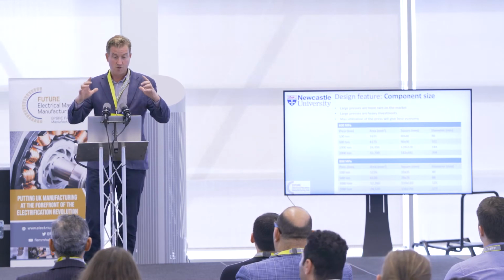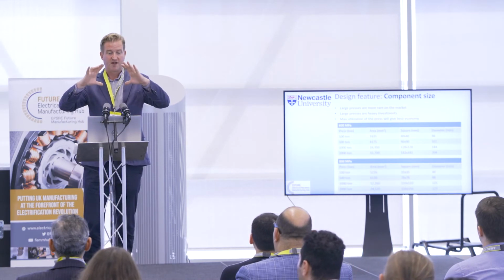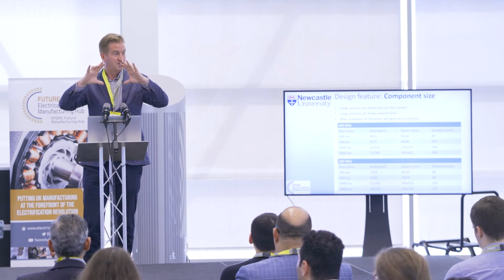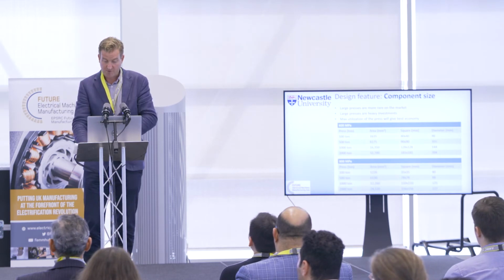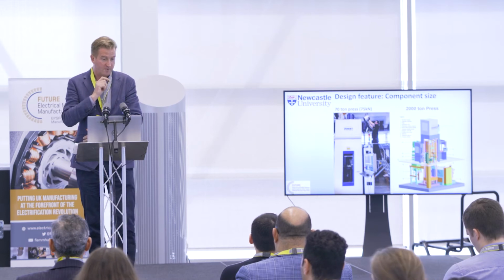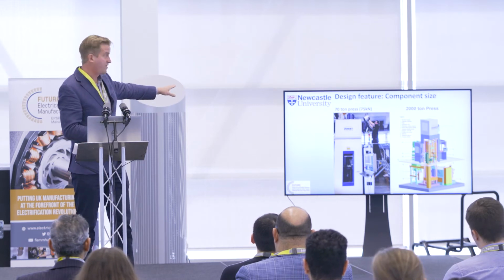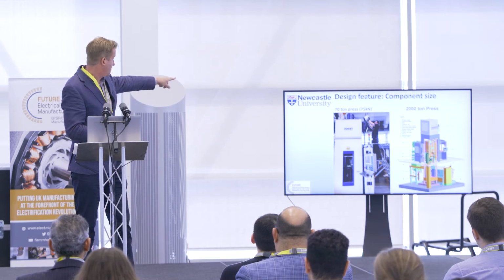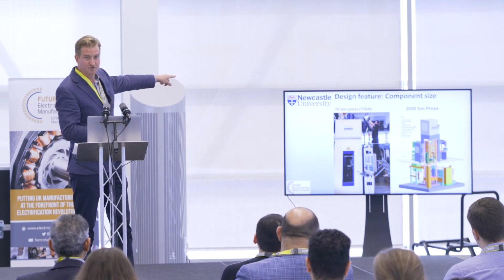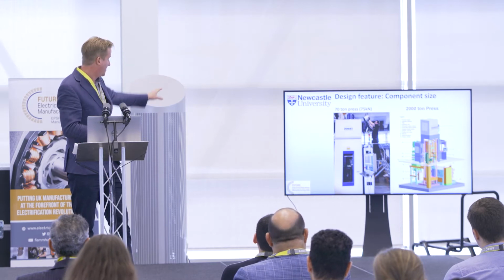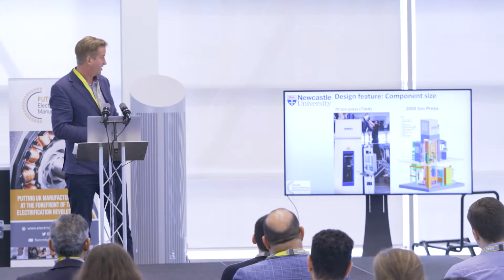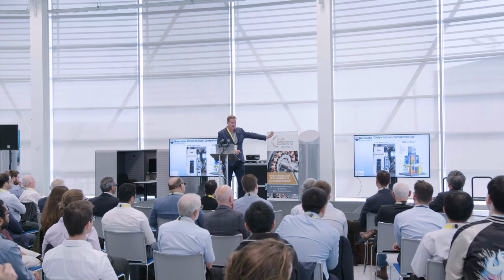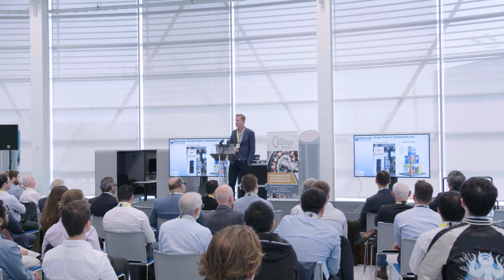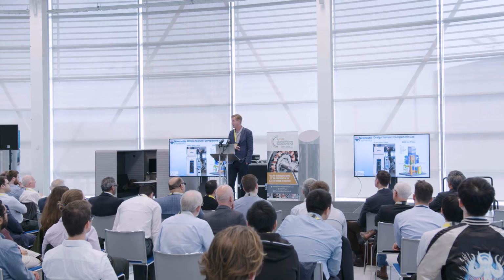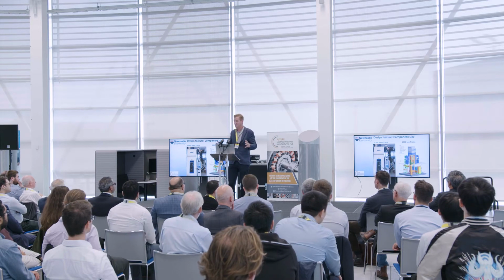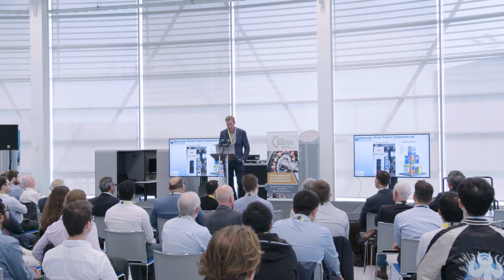If we're wanting to compress something with a reasonable diameter, say 200 millimeters, we're going to need a 2,000-ton press. And the problem is they're a little bit few and far between. You see the 70-ton press on the left there. The person on the ladder is literally pouring SMC from the metal tin into there. On the right is a 2,000-ton press, and you can imagine the operator being quite small compared to that. So there are few of those around. There's a balance between component size, pressure, and what's actually available to press the stuff.